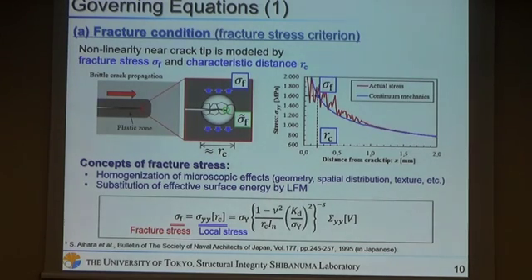In the following slides, we will explain the governing equations. First is the fracture condition based on the fracture stress criterion. In this criterion, non-linearity in the crack tip is modeled by fracture stress and the characteristic distance, as shown in these figures. The concept of the fracture stress is homogenization of the microscopic effects such as geometry, the spatial distribution, textures of microstructure, and so on. The physical meaning of the fracture stress is a substitute for the effective surface energy in linear fracture mechanics theory. Actually, we use the form of this equation for the fracture condition.